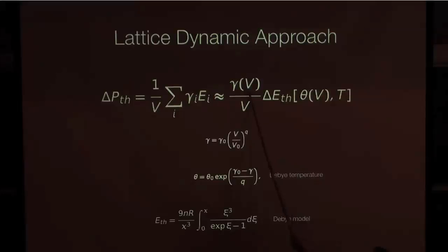But now the Gruneisen parameter is reappearing. Here the Gruneisen parameter is defined a little differently. I don't want to confuse you, but I have to. The Gruneisen parameter here is a conversion factor from energy to pressure. So you have the energy of an individual oscillator that you are studying in a crystal, and then you have a Gruneisen parameter for that particular vibrational mode. I know, sigh, right? Then you can sum over it, and you get the entire vibrational energy, which is almost impossible for us experimentalists to do.